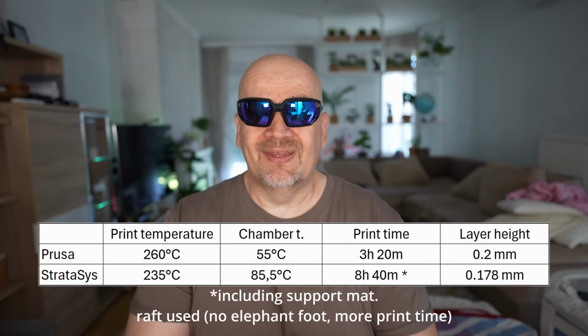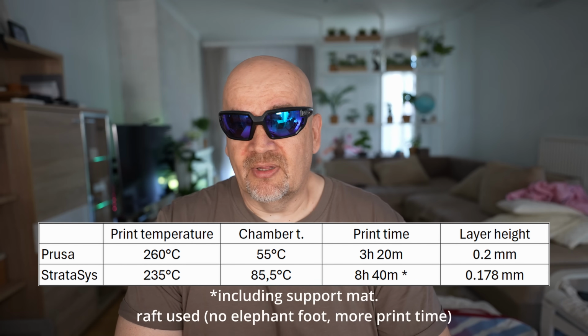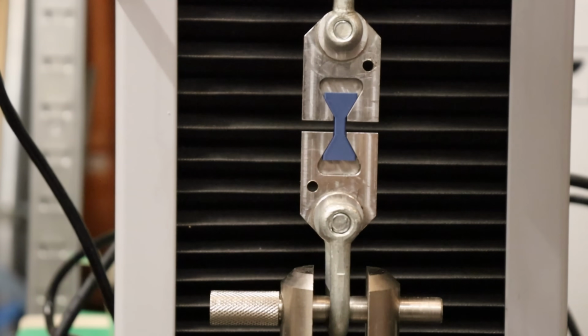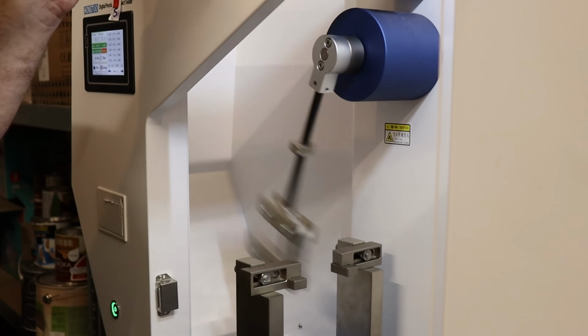Of course it's obvious that these two ASA filaments are quite different. We can see this even from the print settings. Here I collected a small table with the key differences in the print parameters, and I can see only 2.5 advantages of the Stratasys ASA over the Prusament. One, we still have a little bit better layer adhesion, even if it was printed at significantly lower temperatures. The second very important property for the ASA is that the Stratasys version is significantly more temperature resistant compared to the Prusament. Unfortunately, another important property for the ASA would be the impact resistance, and here the Stratasys ASA is very brittle, almost like some PETG.